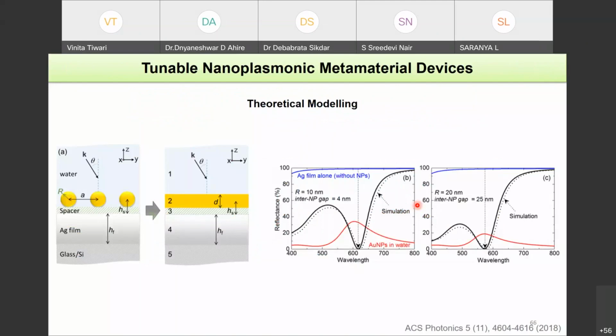So again, how do you do the theoretical modeling of this? As I mentioned, the effective medium theory, where you can take this nanoparticle layer and try to model this as this layer 2, which is a fictitious layer but a uniform layer of a permittivity that is derived from our effective medium theory, where I have shown you the calculation of beta parallel and beta perpendicular. From that, you can obtain what is epsilon parallel and epsilon perpendicular. And once you obtain that, this is a very easy multi-layer system. So you can use the transfer matrix method here, right?